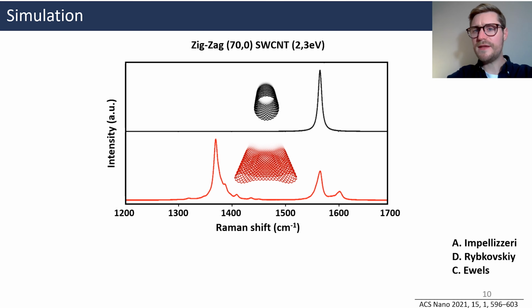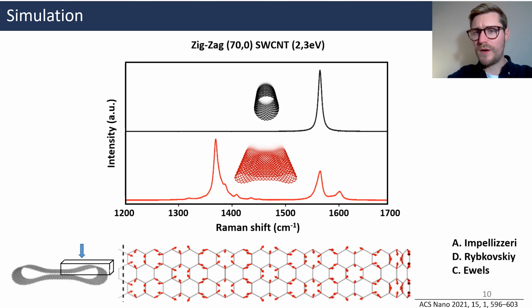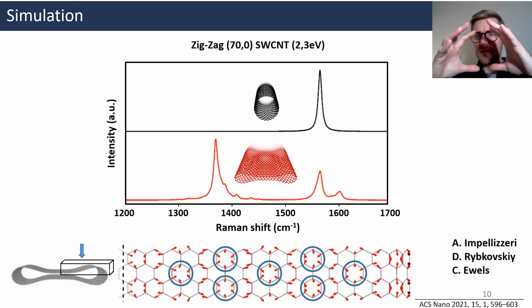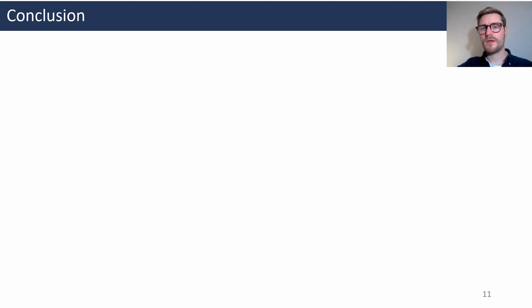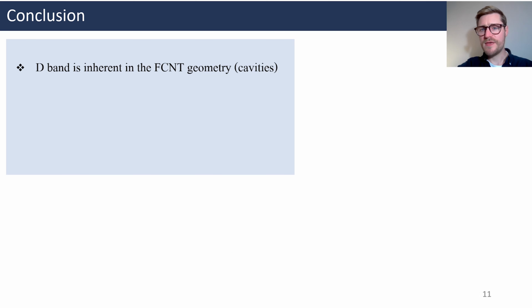Finally, some colleagues did some simulation using the Placzek approximation. They found that the collapse of a tube provoked a new band near the D-band region. Qualitatively, when looking at the associated vibration, it's possible to recognize the breathing-like mode of the carbon hexagons associated to the D-band in graphene. To conclude, I showed you today that in flattened carbon nanotubes, the D-band is inherent to the geometry of the object. So, the D-band cannot be used for structural defect density measurement in flattened carbon nanotubes.